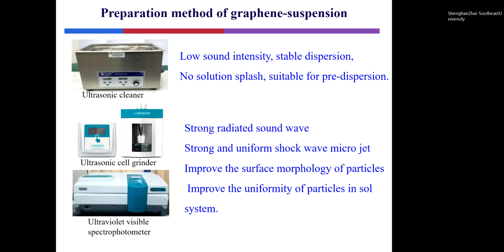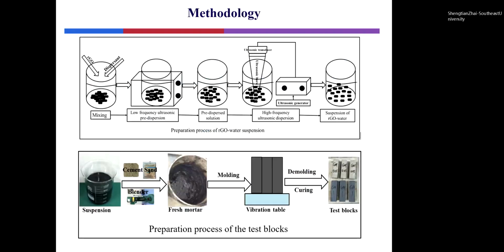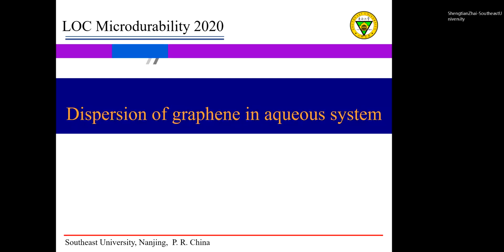Ultrasonic cleaning instrument has a low sound intensity, stable dispersion, and no solution splash, so it is suitable for the preparation of dispersion equipment. Ultrasonic probe renders the stronger radiant sound wave at the end of the probe, so the strong and uniform shock wave and micro jet are formed in the reaction liquid. This picture shows the preparation process of the graphene suspension and the test methods. Next, please look at part 3.